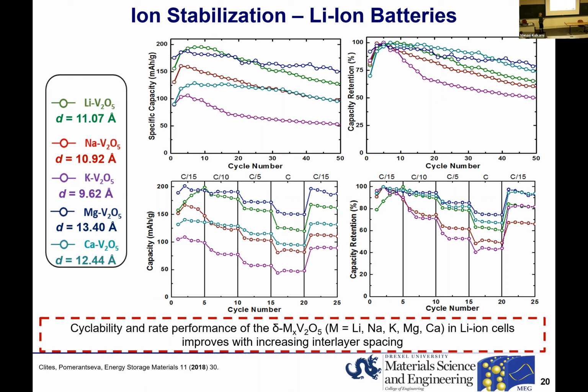So what we found through the cycle life and rate capability experiments is that the magnesium pre-intercalated phase, shown in blue on these graphs and also blue in here, gives us the best performance. It shows the best rate capability, it shows the best cycling stability. And this is also the phase that has the largest interlayer distance in our synthesis. So we concluded that for the cycling of small lithium ions, increasing interlayer distance might lead to favorable performance, not only from the point of view of capacity, but also electrochemical stability.